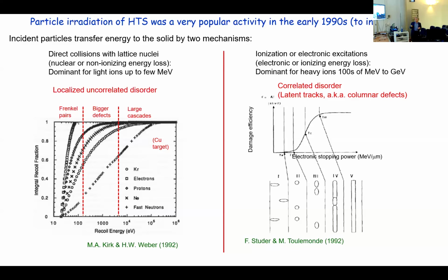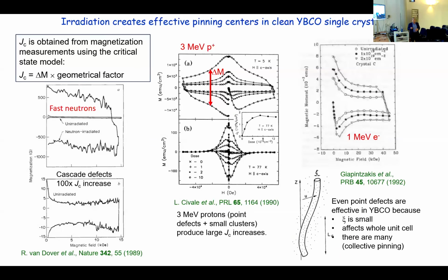That is dominant for light ions, for protons, electrons, and neutrons, up to a few MeV. The other option is very high energies, hundreds of MeV to GeV, with heavy ions, and those heavy ions transfer energy in a completely different way. They transfer energy to the electronic system of the material, and they produce columnar, correlated disorder. If the energy transfer is not enough, they produce a collection of correlated spheres of damaged material, then eventually discontinuous columns, then eventually continuous columns of amorphous material. Irradiation produces very effective pinning centers in clean YBCO single crystals, and that was mostly studied in the 1990s.